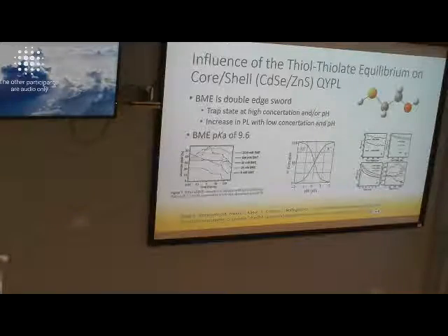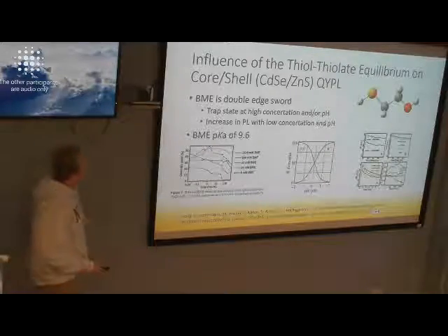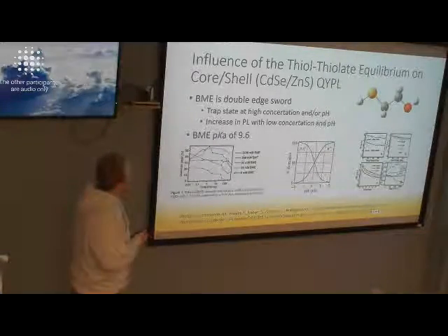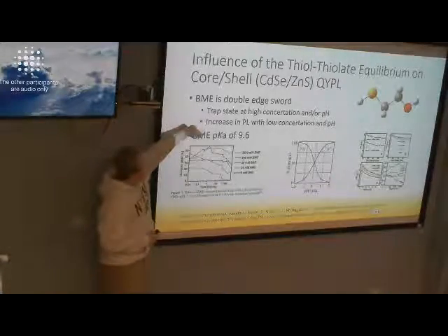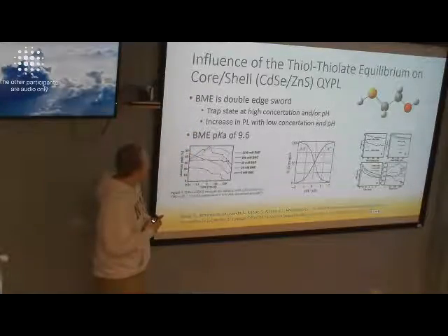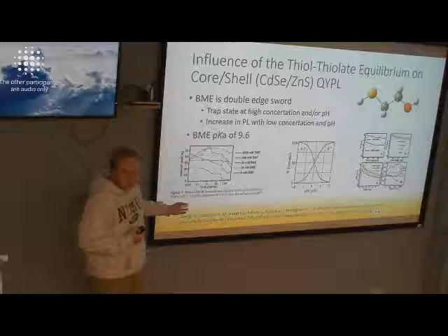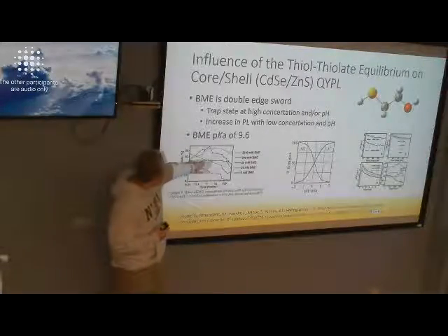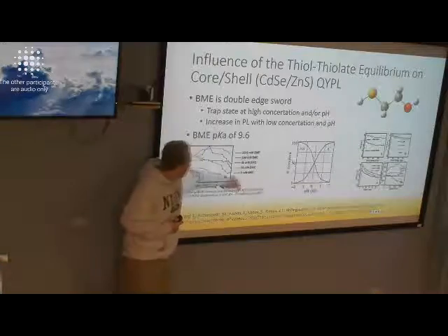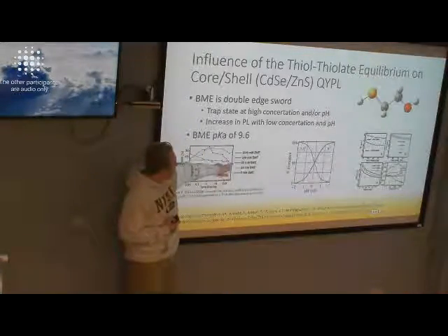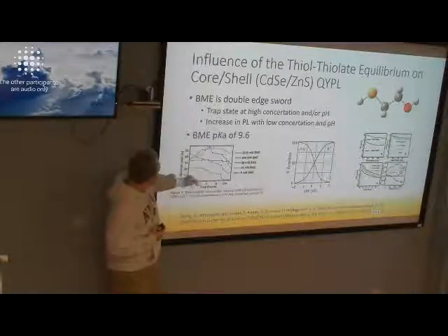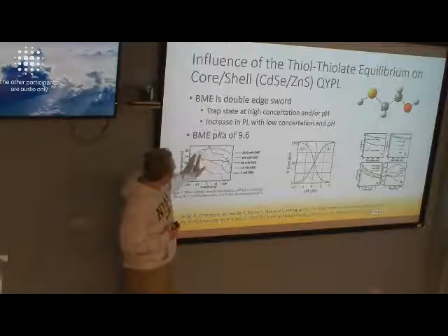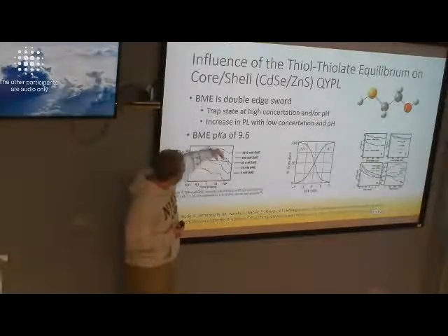And then another study, they used the alcohol form instead of the acetic acid one. And here, if they didn't use the phrase double-edged sword, I did, and the reason for that is here's the black line which has no thiol compound in it, and as we slightly increase it, the quantum yield goes up by like 60%, and then after some time, some of it drops.